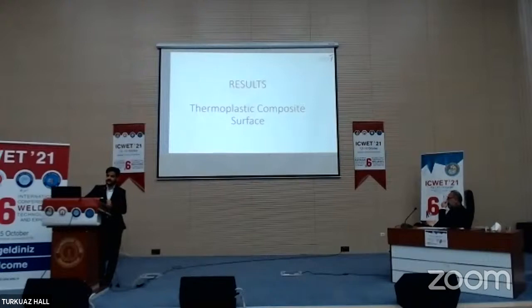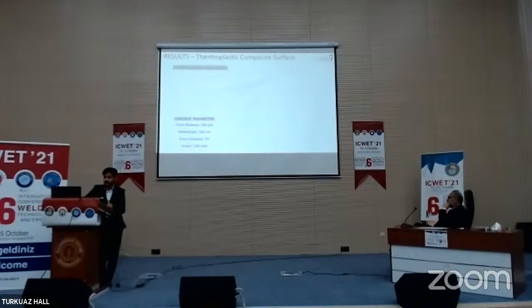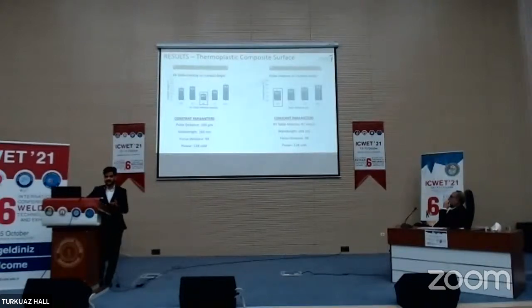For now, we have discussed the results for the titanium alloy surface, and it's time to compare with the thermoplastic composite surface. We applied the same procedure for the thermoplastic composite surface, and we obtained 45 millimeters per second as the speed giving the minimum contact angle, which means the wettability of your material is highest at this point. Then we also optimized the path distance, and we observed similar results as in the titanium alloy surface. Again, a 100 micrometer path distance is a very good option also for the thermoplastic composite surface.